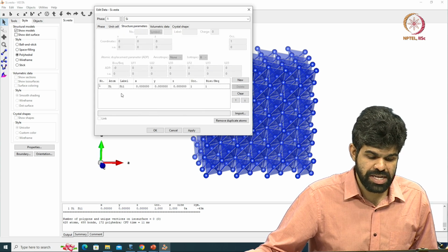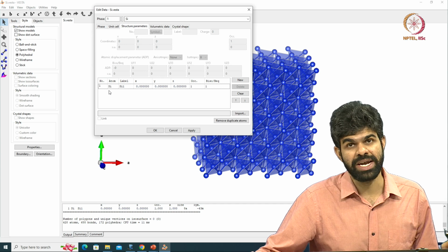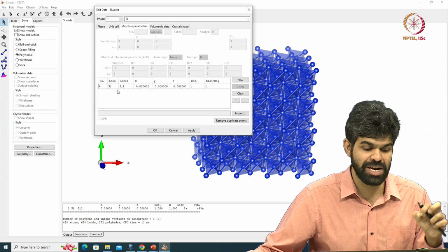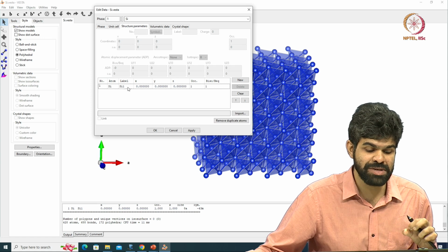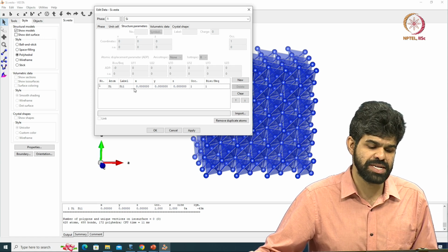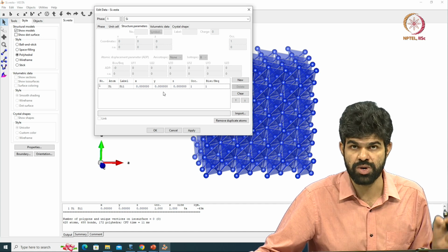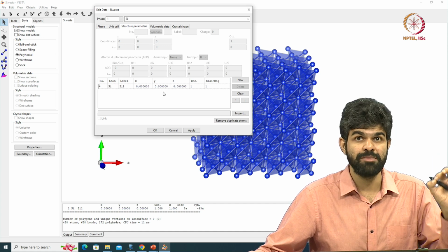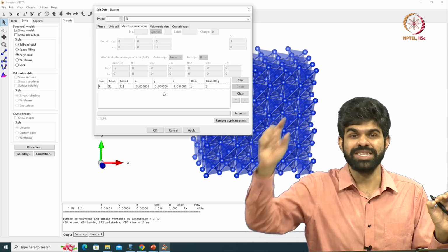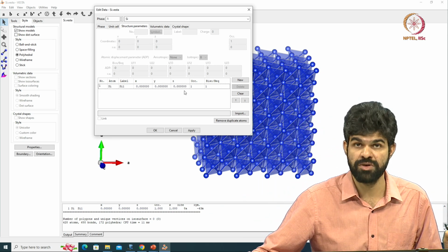Then what am I going to do? I have to now place the atoms. The template is given by the space group. Where am I placing the atoms? I give the x, y, z positions for atoms. For silicon, it is quite easy. I just put x, y, z at 0, 0, 0, wherever there is origin. But then the symmetry repeats it everywhere else. There is a silicon at 1/4, 1/4, 1/4 in this structure.